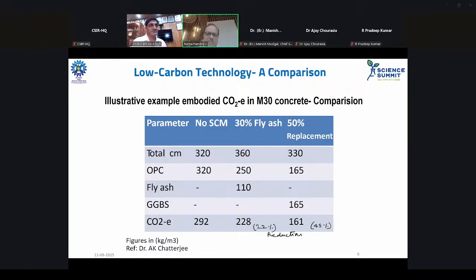Just for comparison, if you use only OPC, no SCM, that is the second column, out of the total cementitious material of 320, all is OPC, no other material is used. The carbon dioxide emission would be about 292 kg per meter cube. Therefore, if you replace it by 30% of fly ash, 292 will become 228.